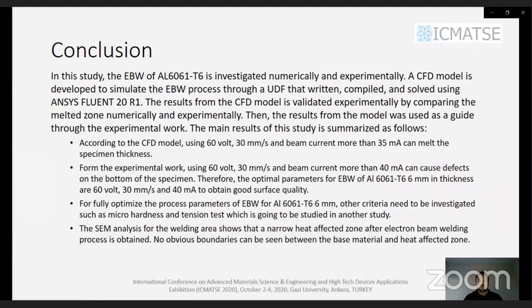To fully optimize the process parameters of the electron beam welding for aluminum, other criteria need to be investigated, such as microhardness and tension test, which is going to be studied in another study. And the SEM analysis for the welding areas shows that a narrow heat affected zone is obtained after the electron beam welding process. No obvious boundaries can be seen between the base material and the heat affected zone.